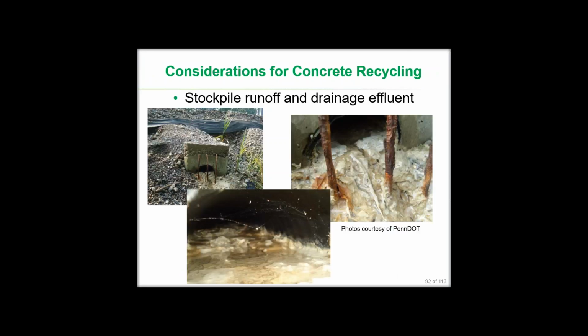I mentioned earlier about drained bases versus undrained bases. One of the concerns that we have with using crushed concrete in base courses when there is drainage, or even when we're stockpiling it prior to use in an undrained base or a concrete paving application, is what happens to that runoff from the stockpile. Because what happens is a byproduct of the hydration of cement is calcium hydroxide, and that's a very soluble material which is easily removed, and when it's dissolved it breaks down into calcium ions and hydroxide ions, and the hydroxide ions of course drive the pH up. And then that hydroxide ion may combine, as I mentioned earlier, atmospherically with the atmospheric carbon dioxide to form calcium carbonate, or what's sometimes called calcareous tufa.